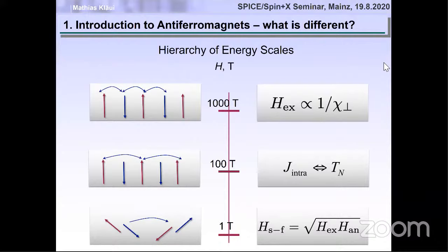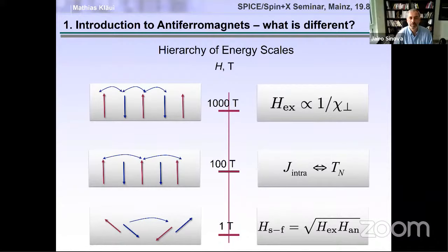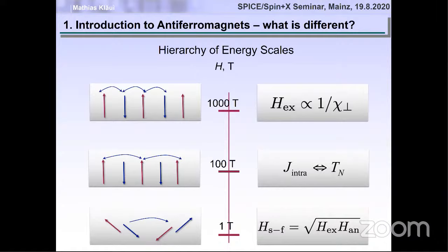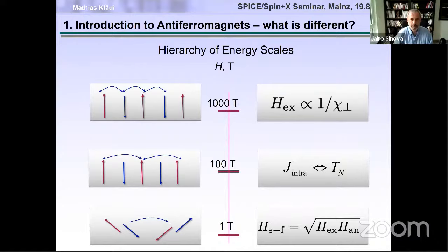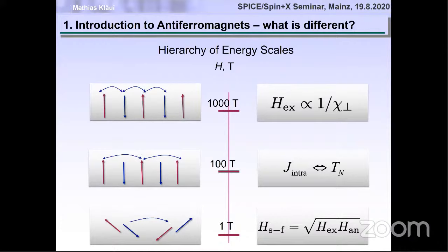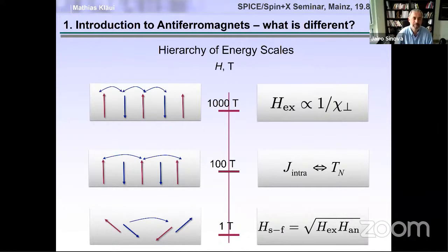That's all. Well, no, I simply don't understand it, because suppose I take, for example, a simple system like cubic perovskites, then I can include only inter-sublattice exchange, only nearest neighbor inter-sublattice exchange, and that's enough. I don't have to worry about further nearest neighbor coupling. And that will give me everything I need. It will give me magnetization, it will give me Néel temperature, it will give me susceptibility, it will give me spin-wave spectrum, and so on. Right. If we have a more complicated system like frustrated, then maybe you have to worry about all this. Otherwise, I don't think there is inherently a problem here.